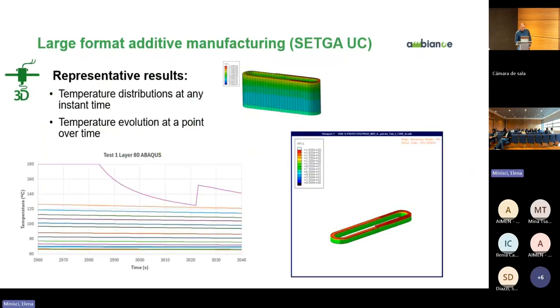So here, for example, we have one of these simulations for one of the earlier test demonstrators performed at AIMEN. Here we can see how it's building this simple part layer by layer. The representative results are temperatures. What we are seeing now on the screen are temperature distributions at any time, at any point. In particular, what we are looking for is to predict the temperature in a point of one layer when the next layer reaches the same point, which is the temperature it finds on this substrate, because this will determine the quality of the adhesion between the two layers.